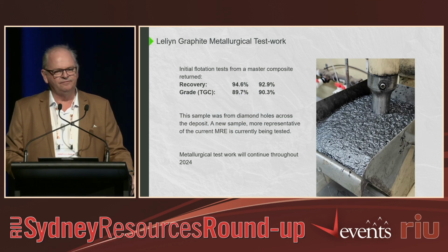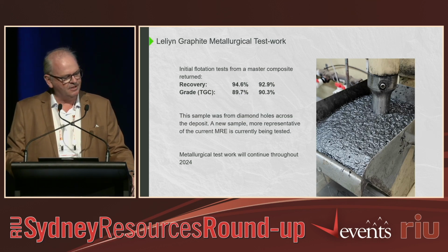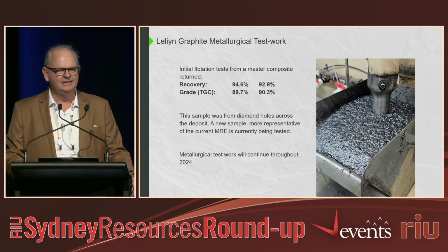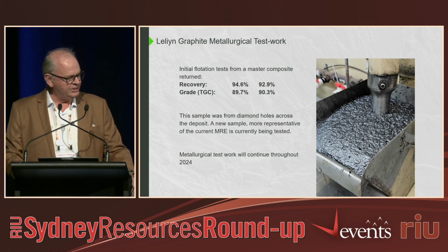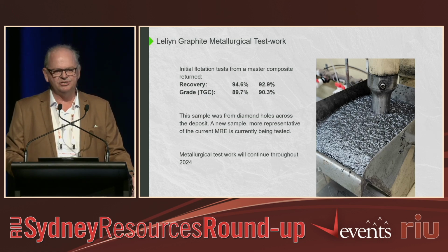Now, we've done some initial float test work. We released a few figures a few weeks ago with the mineral resource estimate. We're doing the initial flotation optimisation work. You can see there these initial results. We've got quite good recoveries, above 90%, which is very good. The grades were around 90%. Since then, we've had grades higher than that. The target is a concentrate grade of around 94-95%. And obviously recovery as high as you can get.